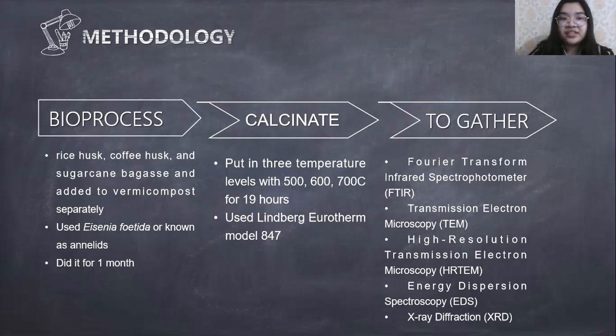We also use this to get silica oxide. We get it from the agro-industrial waste without doing vermicompost bioprocesses. We use the same procedure as the last time. We also use commercial synthetic silica oxide Aerosil 132 that was provided by Degussa AG to be compared to what we made. Next, to eliminate some organic matter, we calcinated it. The three agro-industrial wastes were put at three temperature levels: 500 degrees Celsius, 600 degrees Celsius, and 700 degrees Celsius for 19 hours. We used Lindberg Eurotherm Model 847.